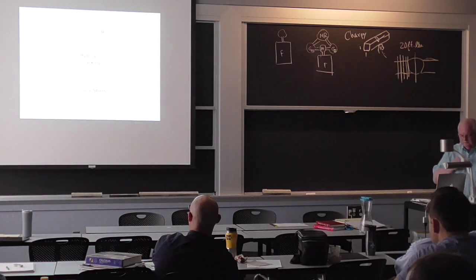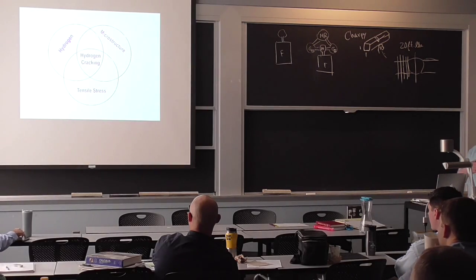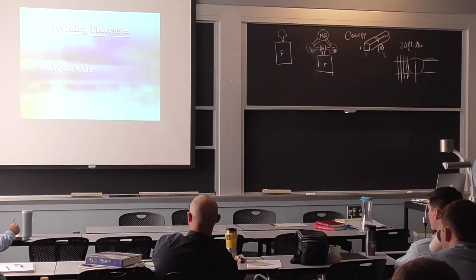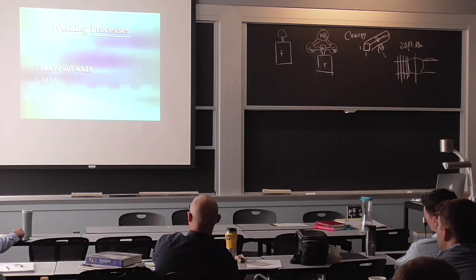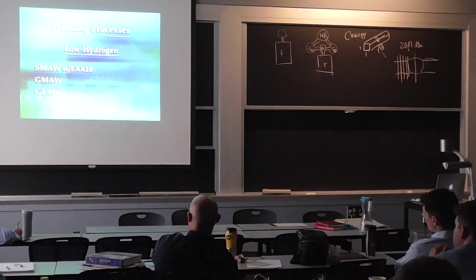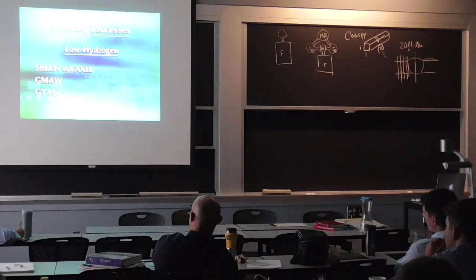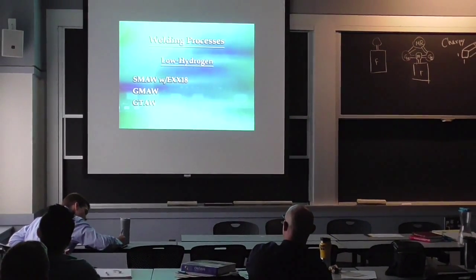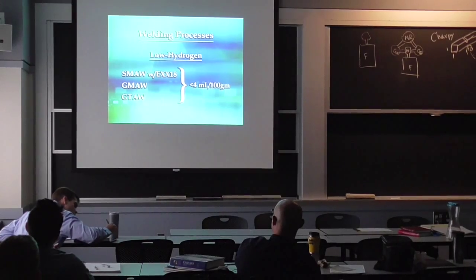Hydrogen cracking results when three independent conditions occur simultaneously: hydrogen in the weld, a crack-susceptible microstructure, and tensile stresses acting on the weld. If one or more of the conditions are removed or reduced below a threshold value, hydrogen cracking will not occur. Because the susceptibility to hydrogen cracking increases with increased hydrogen content, this demonstration video will focus on limiting hydrogen in the weld. Welding processes such as shielded metal arc welding with AWS EXX18 type electrodes, gas metal arc welding, and gas tungsten arc welding are considered low hydrogen welding processes. The hydrogen content of a weld is measured in milliliters per 100 grams of deposited weld metal. A typical low hydrogen process produces welds with 4 milliliters of hydrogen per 100 grams or less.